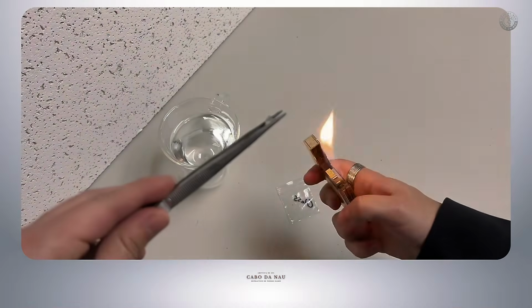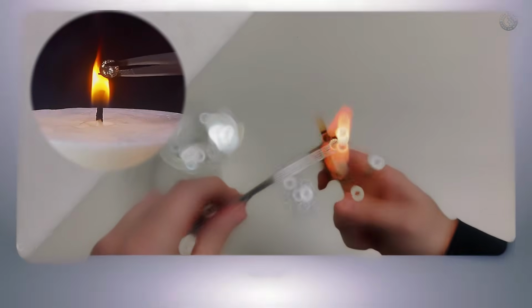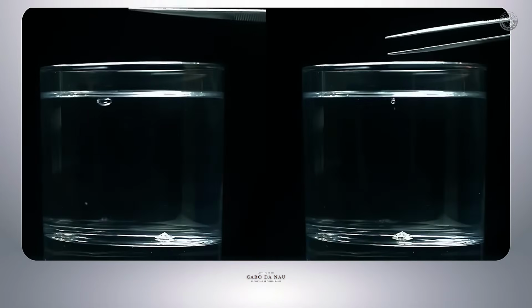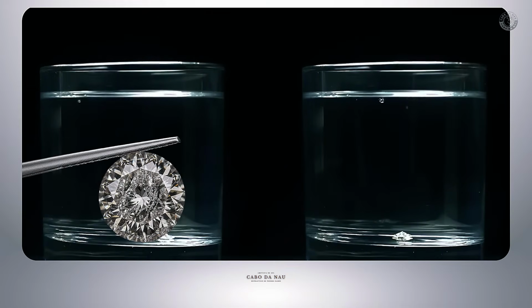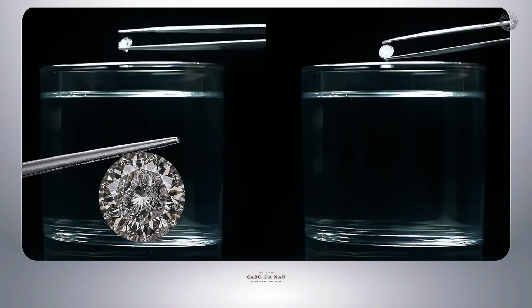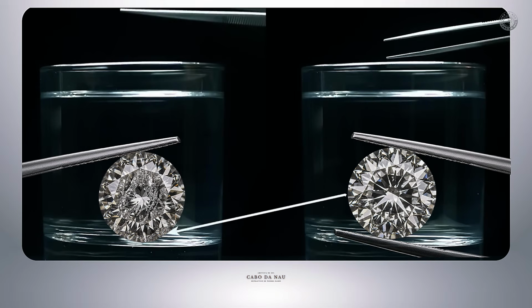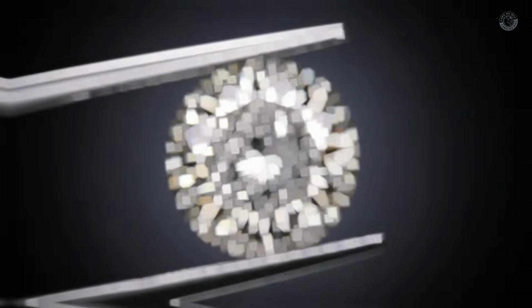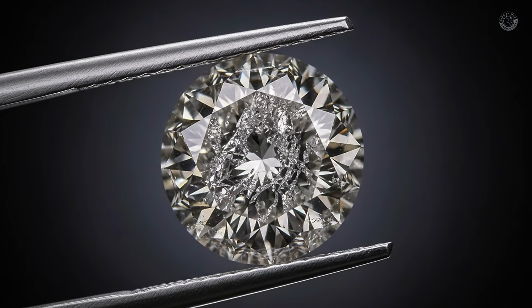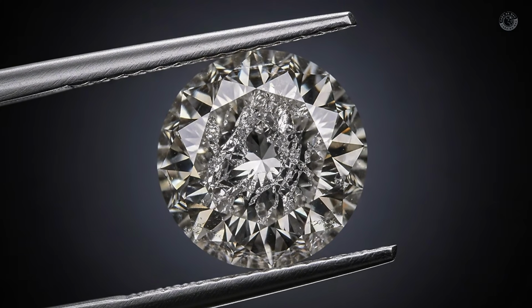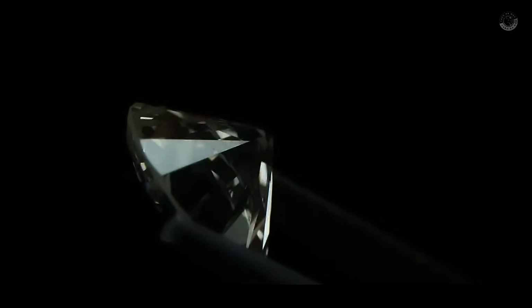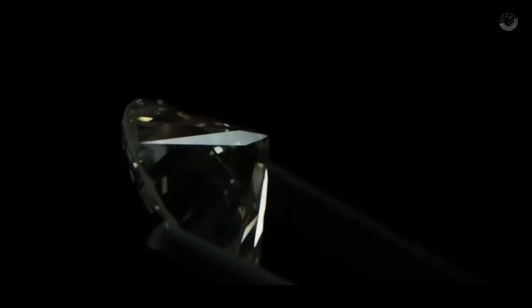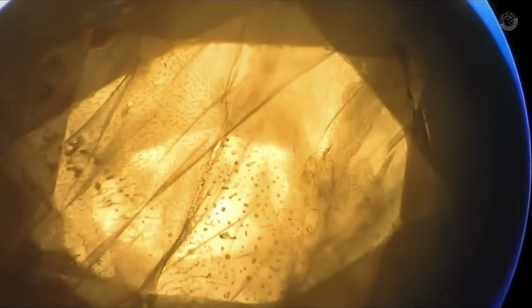But how can you test your diamond without investing in expensive equipment? On screen right now, you're watching two stones take the same flame and the same dunk in cold water. The one on the left fills with internal fractures and turns cloudy. The one on the right stays intact. That's how controlled heat can separate a cheap fake from a real diamond. Glassy simulants often fail under rapid heat and quench. Diamonds' high thermal conductivity and rigid lattice shed heat fast and hold up far better. In seconds, the truth shows up.